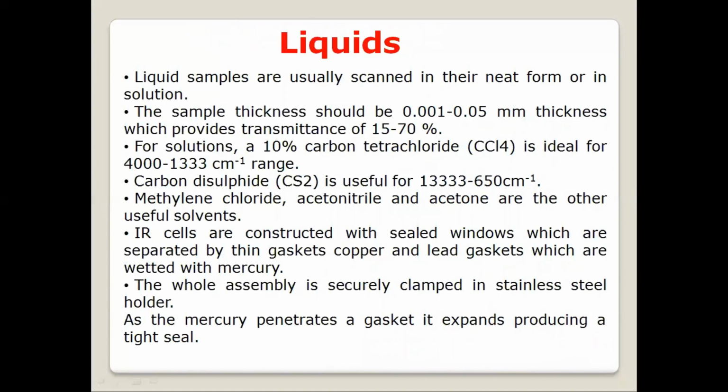In case of liquids, liquid samples are usually scanned in their neat form or in solution. The sample thickness should be 0.001 to 0.05 millimeter, which provides transmittance of 15 to 70%. For solutions, a 10% carbon tetrachloride solution is ideal for the 4000 to 1333 per centimeter range. Carbon disulfide is useful for 13333 to 650 per centimeter. Methylene chloride, acetonitrile, and acetone are other useful solvents.